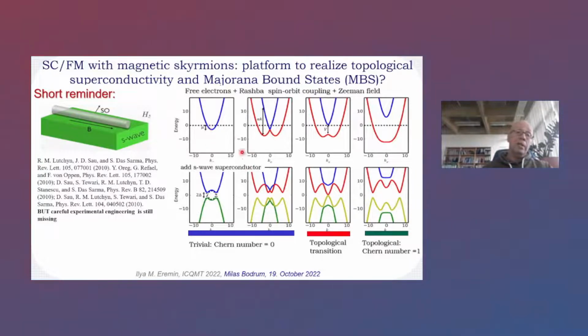In that case, it has been shown by virtue of a very simple calculation that if you start with a simple two-dimensional electron gas, you split it by virtue of the spin-orbit coupling, you apply the Zeeman field, and if you tune the parameters in the right regime, the Fermi level crosses only one of the bands, and this band will be hosting spinless fermions. If now you put an s-wave superconductor in proximity to it, you will actually realize a topological superconductivity which should host Majorana bound states.